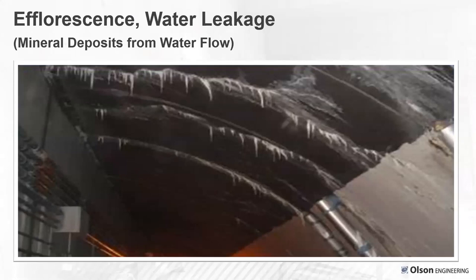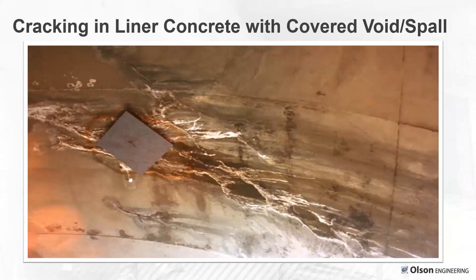NDE techniques can detect horizontal cracks, other types of deterioration mechanisms, and tell you the severity of damage. Here's an example of cracking in a tunnel liner — under that metal plate is actually a big hole, a void, with spalled-off concrete. This was pretty severe. Some of that efflorescence is reddish colored, which indicates corrosion of the rebar is also likely going on. That's a pretty severe case of a void and spall in a tunnel liner, with cracks visible in the liner around it as well.